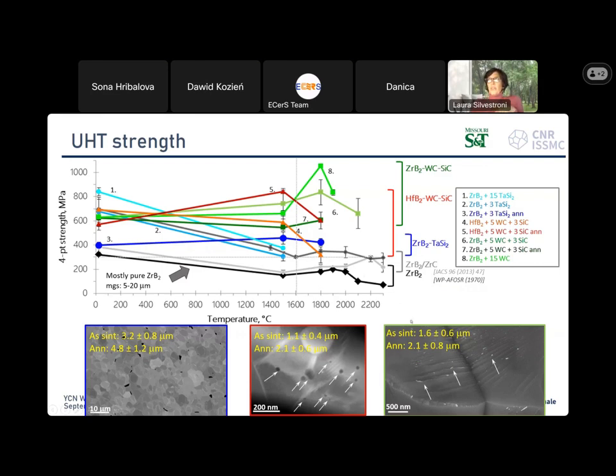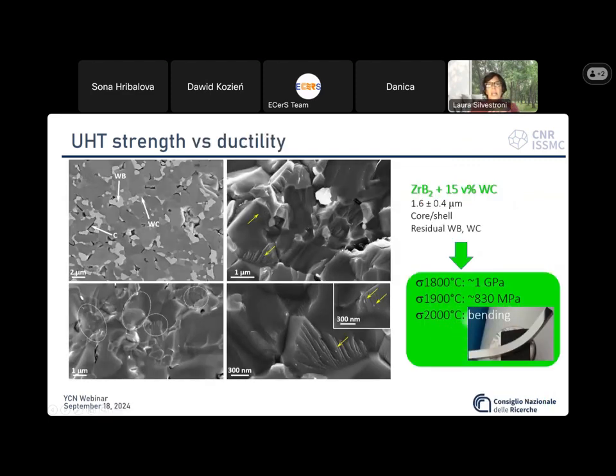Then we arrived at the light green materials, where the annealing, the darker gray, had an opposite effect. It didn't increase the strength because it actually relieved the dislocation structure and increased the size of the tungsten particles, both of which reduced the high temperature strength.